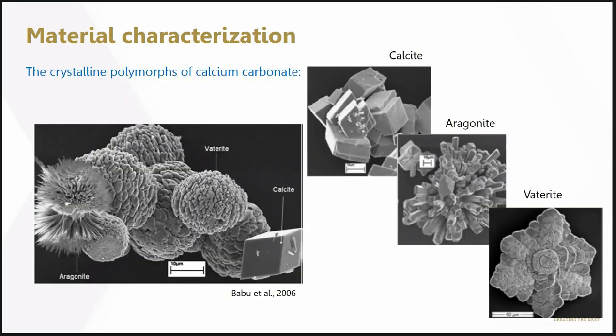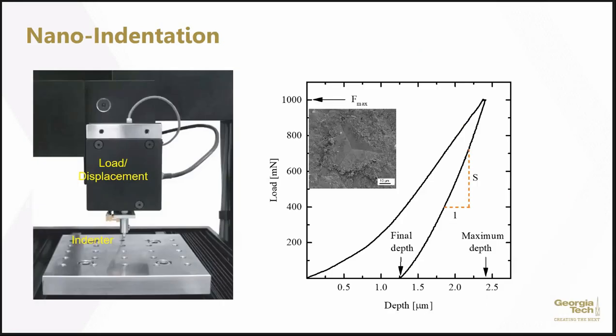We know that there are three popular forms of calcium carbonate: calcite, which will precipitate in large crystals, aragonite in longer, slender crystals, versus vaterite in platy structures. And we see all of those in the earlier SEM images. We wanted to understand the material properties, and the way to look at the crystal-level material strength and mechanical properties is through indentation. So we ran some nano-indentation tests.